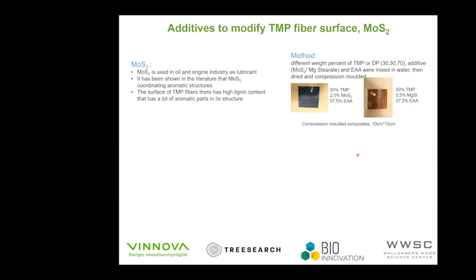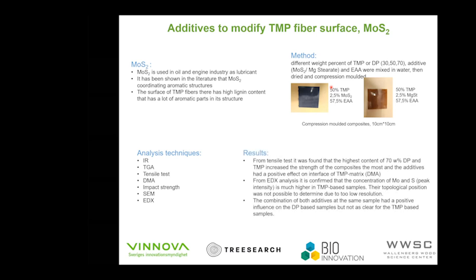So in the method, we used two different types of fibers, TMP and DP, dissolving pulp, as a reference because dissolving pulp is about 95% cellulose, and two kinds of additives, molybdenum disulfide and magnesium stearate. Magnesium stearate, again, as a reference because it's already used in the pharmaceutical industry, and EAA, ethylene acrylic acid copolymer, as the polymer. We mixed it in water and then compression molded it. You can see two examples here. For analysis techniques, we did IR, TGA, tensile tests, DMA, impact strength, SEM images, and EDX analysis at the end.